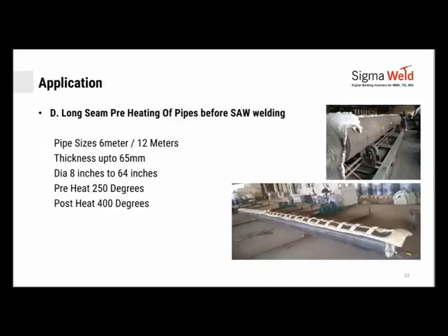This is another classic case where we did preheating of pipes before submerged arc welding for the long seam. And then we did post heating as well. This is a 12-meter long pipe, 25 mm thick. This is a 6-meter long pipe, about 65 millimeter thick. This is the equipment here you can see. And this is another one.